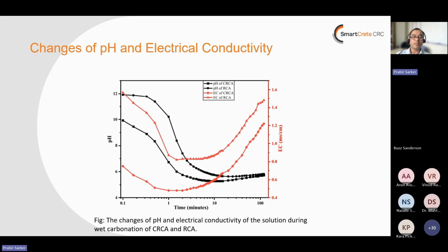So here are some of the results of using this liquid carbonation on recycled aggregates. Both CRCA and recycled aggregate from crushing of cylinders were used here. We can see the horizontal axis is the duration of the carbonation, up to 100 minutes, the vertical axis on the left hand side is the change of pH in the aggregate, and the right hand side is the change of the electrical conductivity. That shows what is happening with the carbonation.